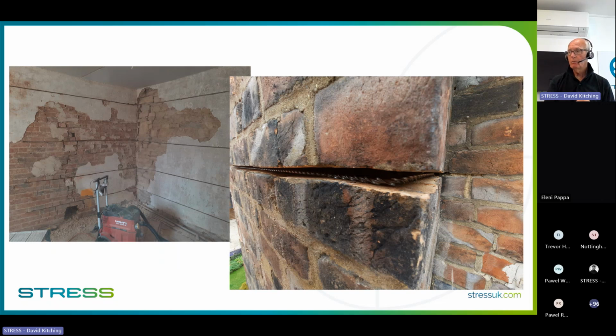You then vacuum it out. You then wash it out, and then you spray a primer in. Then you put the bar in, and then you go in with the polymer modified cementitious grout, and that will bond beautifully to the brickwork. It surrounds the bar, which is helical bar, so it binds to it incredibly well. And when that brickwork tries to move, it will distribute those stresses into the bar and prevent further cracking. So that's why it's really important.